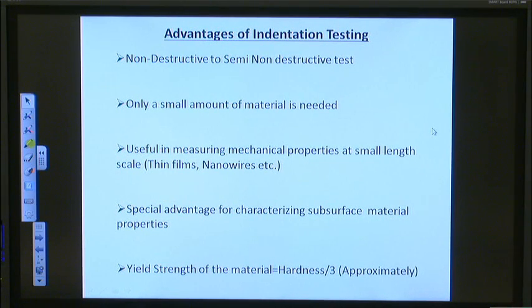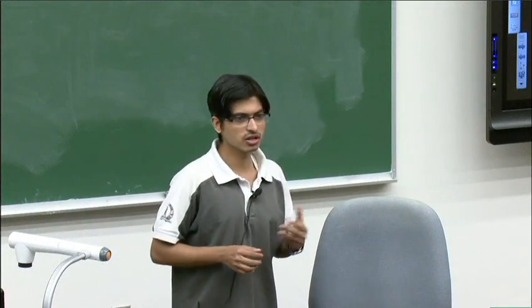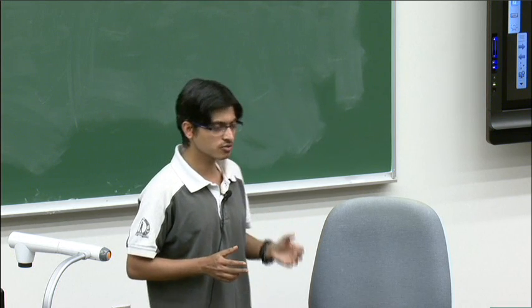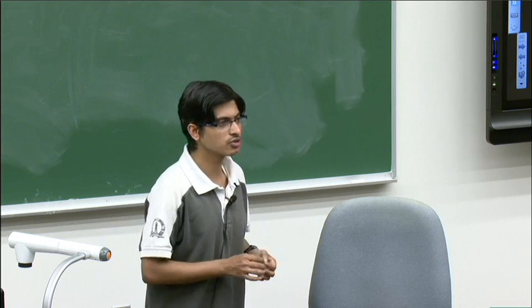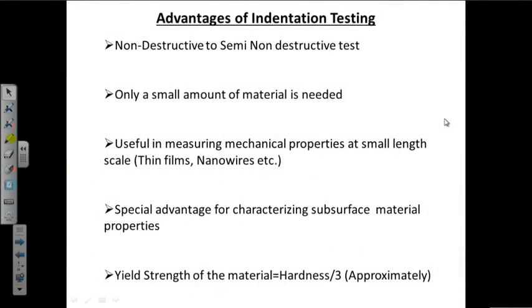And it also has a special advantage for characterizing subsurface material properties. There are several loading and deformation phenomena where the deformation is in the subsurface, and what we can do, we can cut and section those regions, and we can perform small indents at those regions to extract mechanical properties.